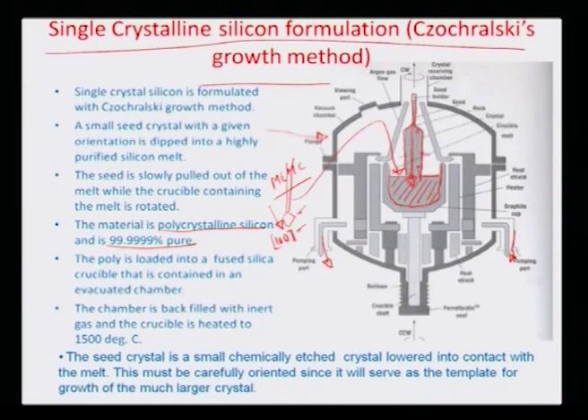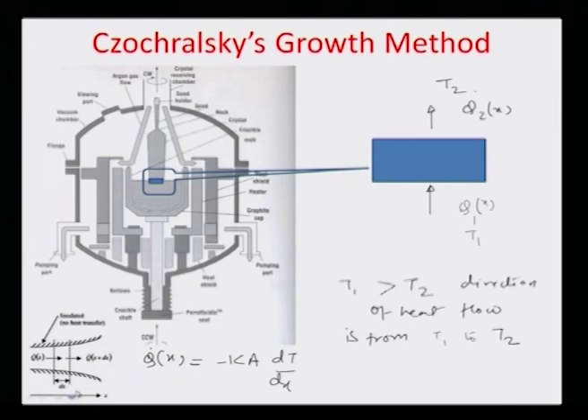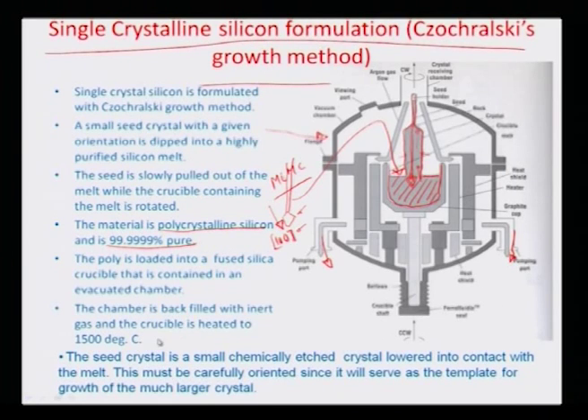So some other nitty-gritty of this process is that the chamber is backfilled with inert gas, and the crucible is heated up to 1500 degrees Celsius. Okay, and the seed crystal is a really small chemically etched crystal lowered into contact with the melt, so that the melt can grow in that direction. It has to be carefully oriented because this serves as a template for growth of the much larger crystals later on. Okay, so that's how the Czochralski growth process is actually executed.